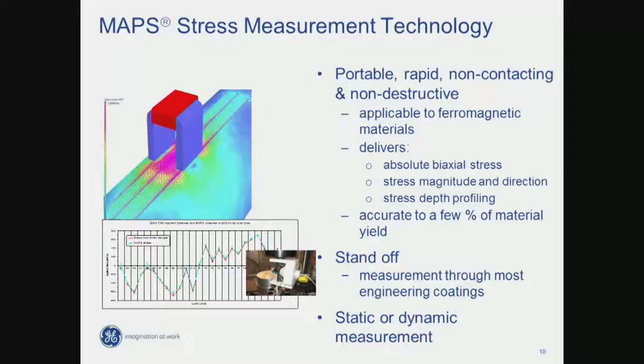And a few things which are useful with a magnetic technique is that you don't have to touch. There's nothing in contact with it. We can stand off from the surface. And that's particularly valuable for flexible pipe because we're talking about being able to stand off the armor wires and sensing through the polymer shield. So there's no intervention within the structure. As long as the gap between our probe and the part we're measuring is not ferromagnetic, it's sort of transparent. So whether it's water, air, aluminium,